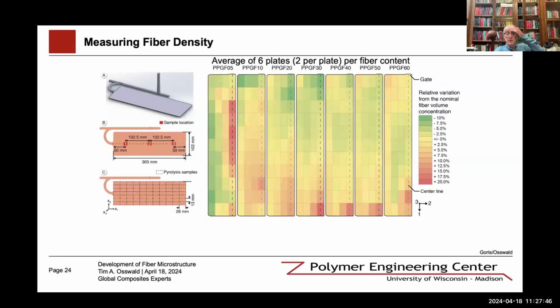Another aspect of fiber density distribution is taking samples, so not looking at the thickness distribution, but rather taking small samples as shown on the left lower side, doing pyrolysis on that and measuring the fiber density distribution. And you can see from left to right, we go from 5% to 60% glass fiber content. There are 6 plates, and each plate, of course, has 2 halves, and it's a symmetric case. So we actually have the averaging of 12 different samples, and you can see how the fiber density distribution changes with fiber content between 5 and 60%.